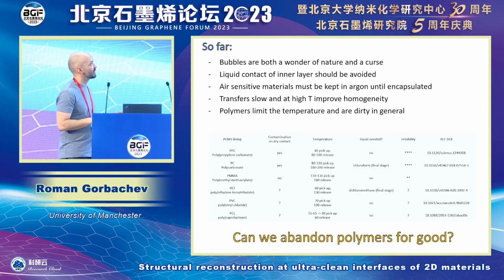And then the polymers that we're using for all of this are really the key limiting factor because you cannot heat them, they melt. You cannot put them in vacuum, they outgas. You cannot treat them with plasma, they etch. There are not so many things you can do with polymers, and we need to move away from polymers as a field in general.